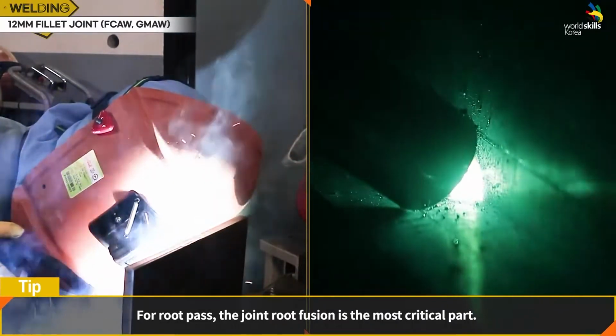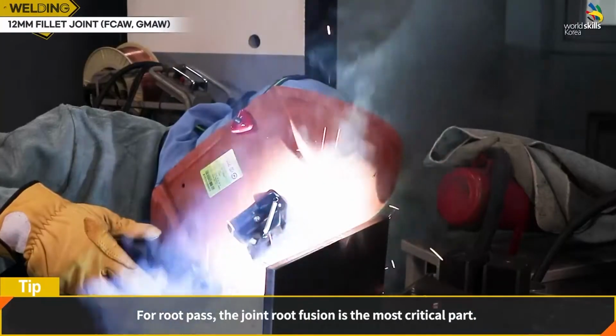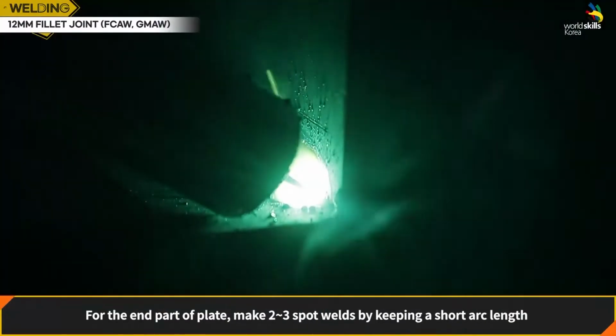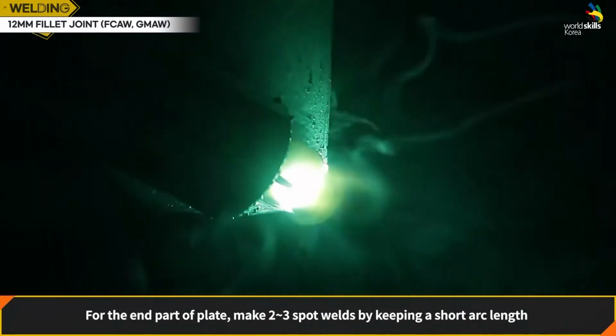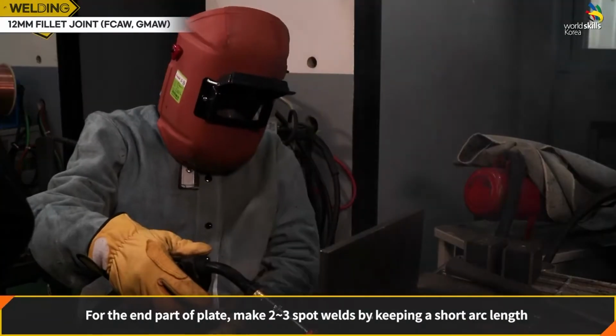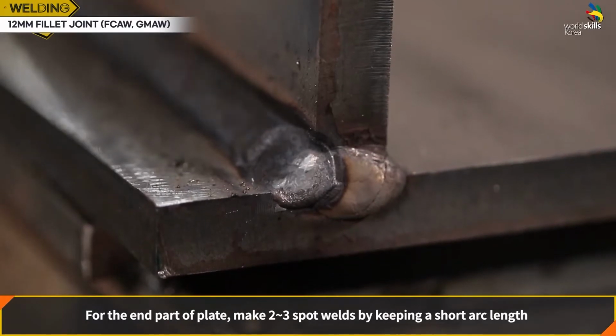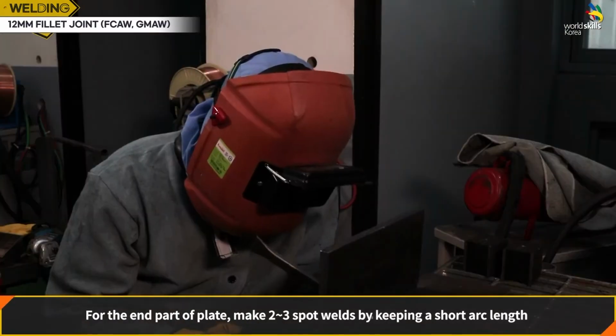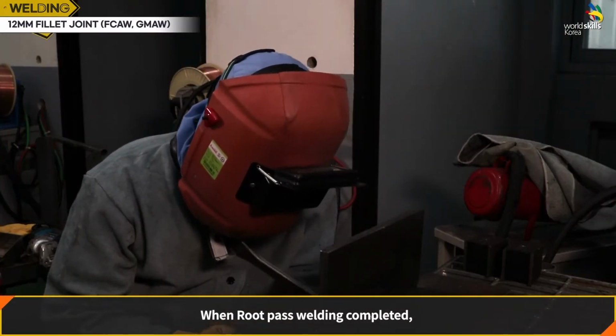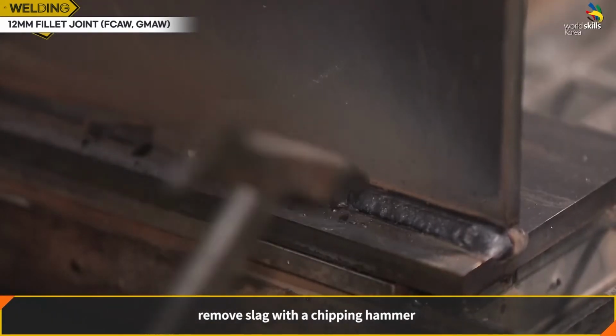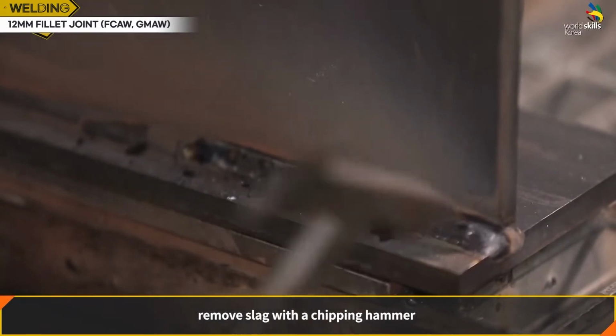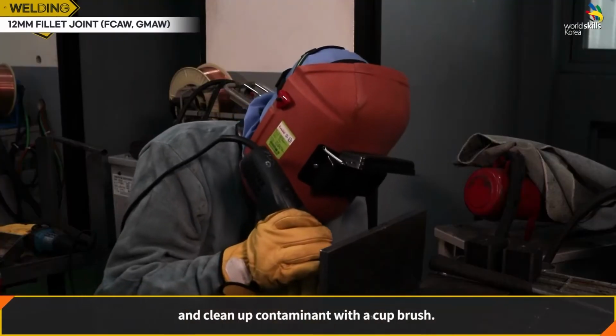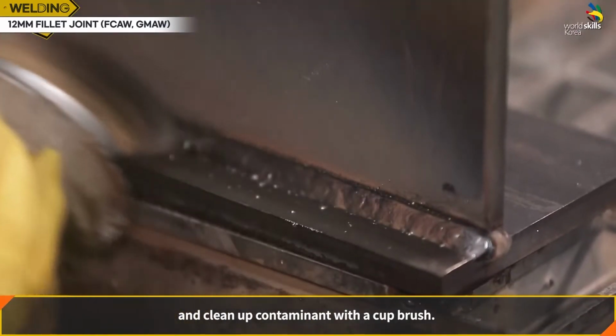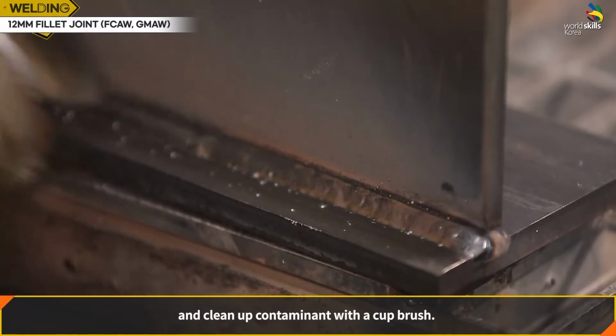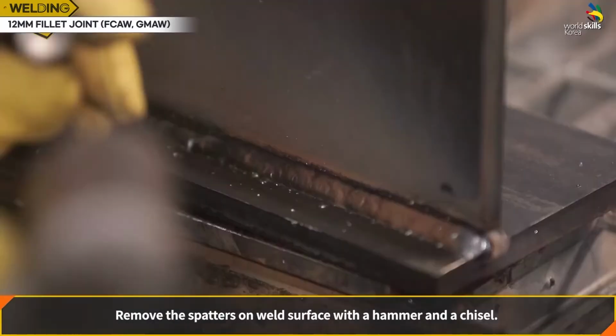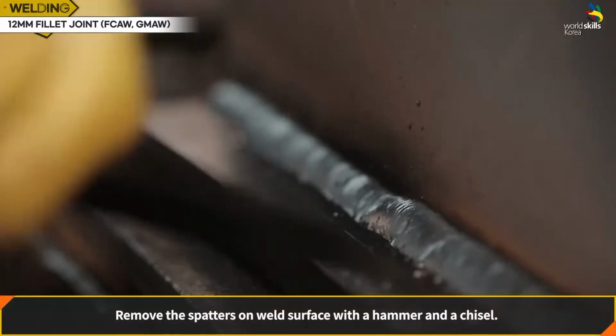For root pass, the joint root fusion is the most critical part. For the end part of the plate, make 2 or 3 spot welds by keeping a short arc length. When root pass welding is completed, remove slag with a chipping hammer and clean up contaminant with a cup brush. Remove the spatters on the weld surface with a hammer and a chisel.